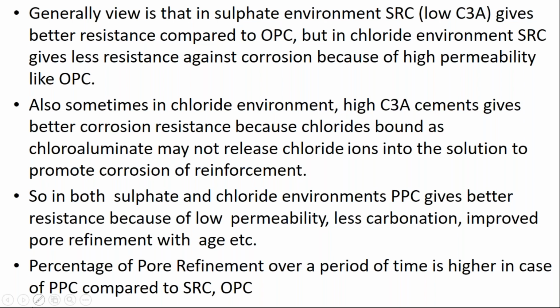So if sulfates and chlorides both are present, SRC cement should not be used and must not be used because it cannot resist the attack of chloride. So you can go in for PPC cement. In case of sulfate and chloride environment, PPC gives better resistance because of low permeability, less carbonation, and improved pore refinement with age. Of course, the CSH gel and all comes into picture there.